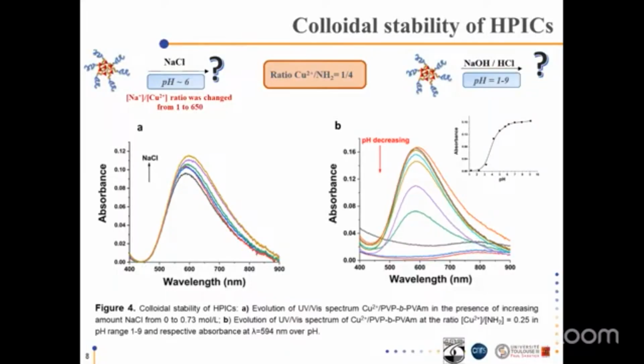It was interesting to evaluate the colloidal stability of HPICs. For this purpose, copper HPIC samples were prepared in the presence of different amounts of 1 molar sodium chloride. As can be seen from figure 4A, UV spectra don't show any changes. So sodium chloride doesn't lead to the destruction of the complex and HPICs remain stable even at very large excess of sodium chloride. It should be added that DLS measurements also do not reveal any aggregation or decomplexation phenomena.